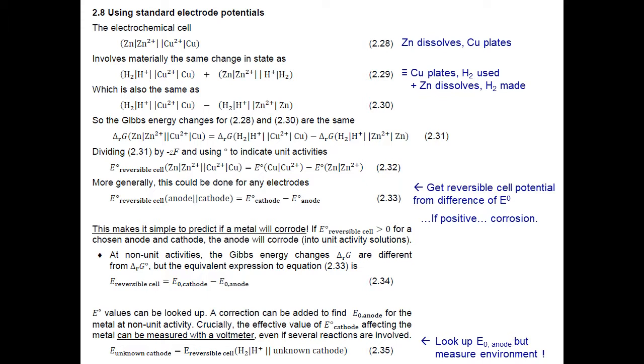In other words, we just need to know the difference in standard electrode potentials of the possible anode and the possible cathode. And if it's positive, when the metal we're worried about is the anode, then we potentially do have corrosion happening. This is if it's at standard concentrations. So everything between 2.28 and 2.33 I've derived for predicting will a metal corrode at standard concentrations.